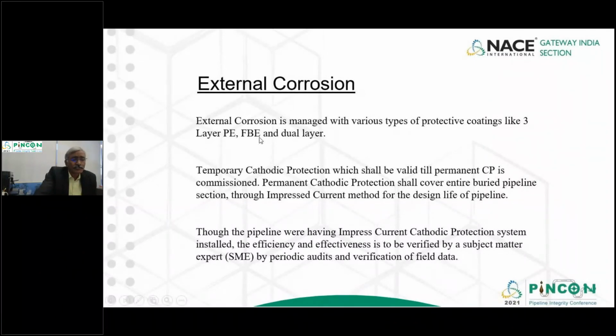External corrosion is one of the serious concerns, the threats we find. Though external corrosion is managed by proper protective coatings like 3-layer PE, fusion bonded epoxy, dual layer, various types of coatings at the pipe mill itself, subsequently we have to provide temporary cathodic protection till the permanent cathodic protection is commissioned. It's a general phenomenon we've seen that people just ignore the TCP even after lowering for so many months. That's very, very dangerous. So that's the information of the data required to implement proper IMS.